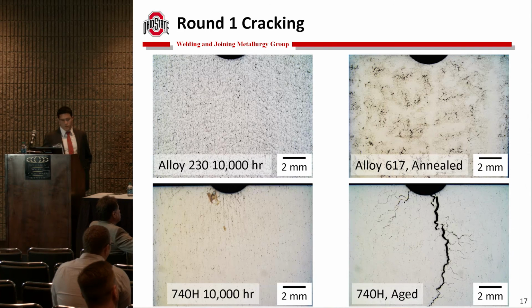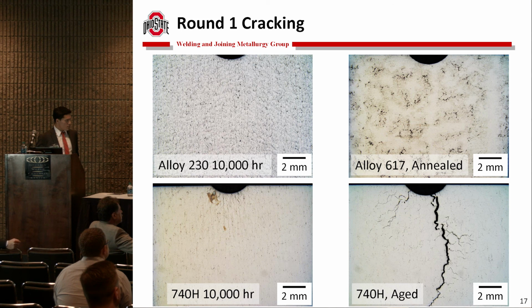So this is what was observed after 1,500 hours at a really low magnification. There was no cracking found in 230 or 617. The 617, which I thought was annealed, certainly wasn't homogenized. And these I think are a dendritic structure, and there's no precipitation in those whiter areas. I'll show you that. There's some minor cracking in the pre-aged 740H, and a huge amount of cracking in the simply post-load heat-treated aged base metal 740H condition, which I would say, at least for me going into this, was pretty expected because the initial grain size is so huge.